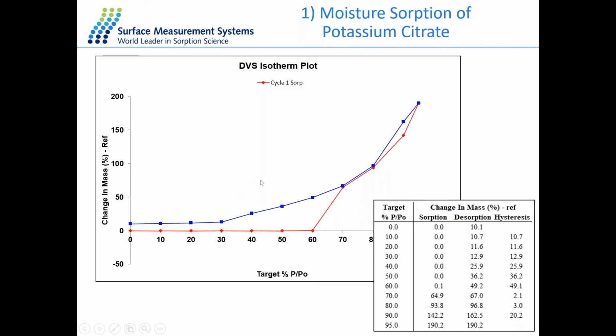So on the left-hand side is the corresponding moisture isotherm, and from the isotherm, it shows a large increase of the water sorption capacity at 70% RH, as well as 90% RH stage, which is indicative of a transition step. The large increase in the water sorption capacity at a certain RH step can also be indicative of hydrate formation, and the shape of this resulting hysteresis is quite typical for the formation of the hydrate. And some other information we can see here is an open loop isotherm, which means an irreversible process.